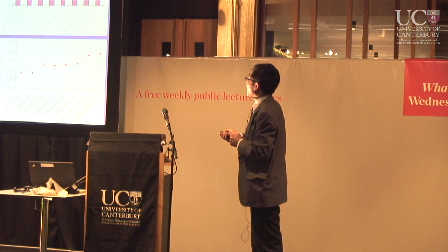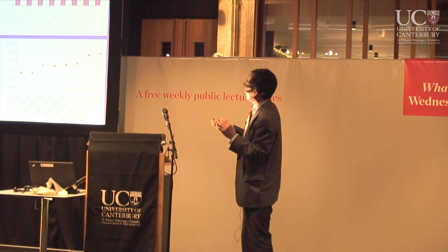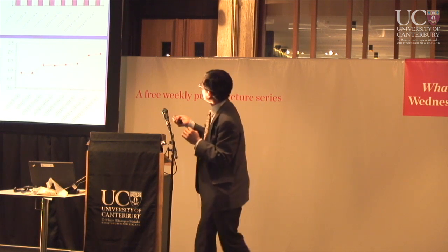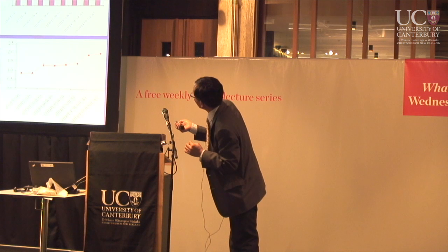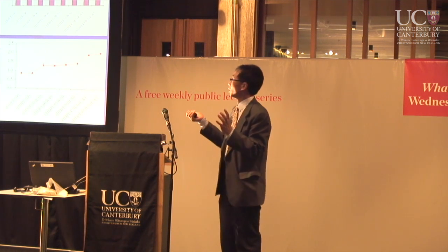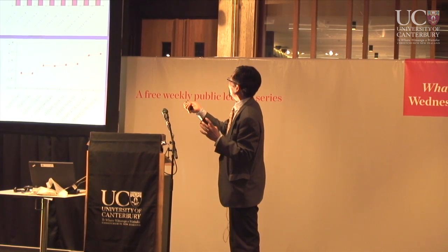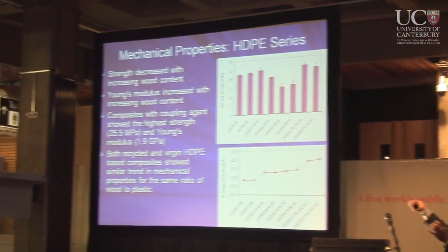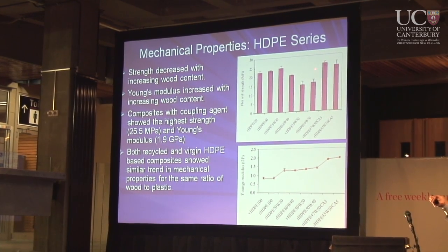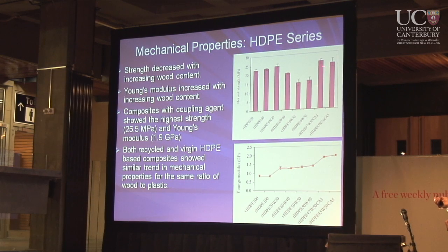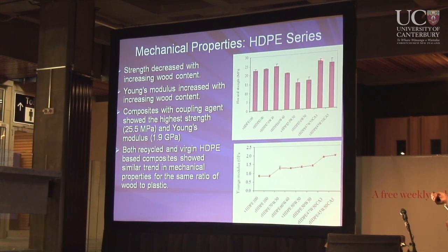And then we look at the mechanical properties. This is the strength. If you have a pure plastic, it's a little bit higher. However, when you add wood, the strength decreases a little bit. But if you add a little bit of coupling agent, the strength increases quite significantly. That is the megapascal of this strength. It's almost 25.